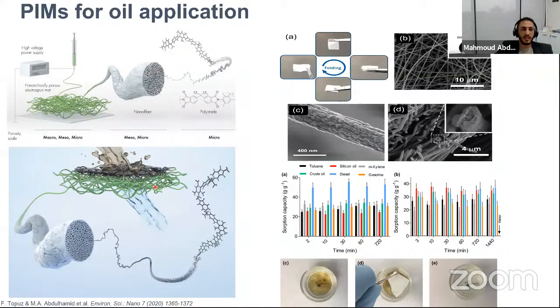a nanosheet made from electrospun fiber. The process of preparation is electrospinning. Then you generate this fiber, which is a nanofiber, but it has meso and micropores inside, resulting from the microporosity of the polymer. And this is how it looks. It's a white material, easily foldable, and this is under the SEM, how the fiber is packing. So it has macropores, mesopores, and micropores at the same time.